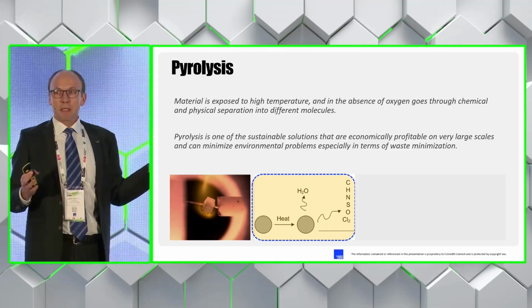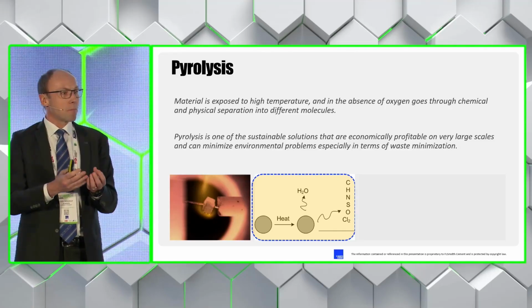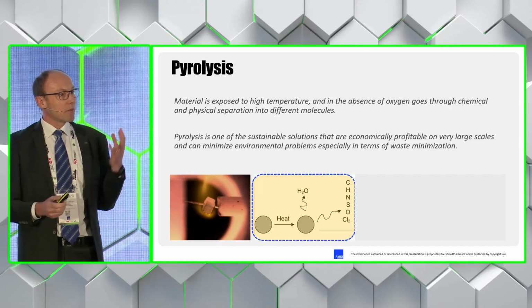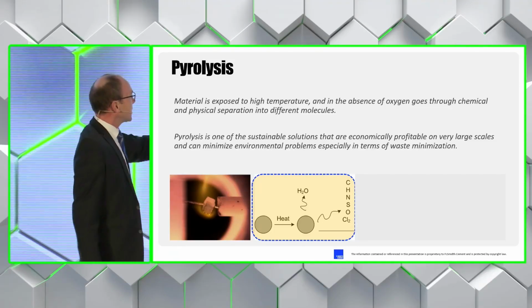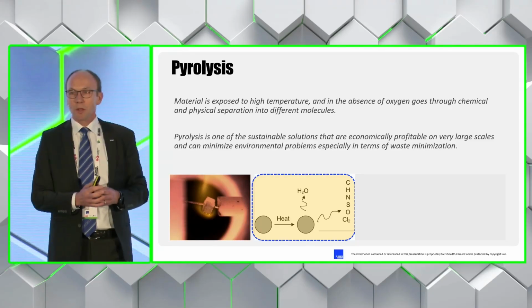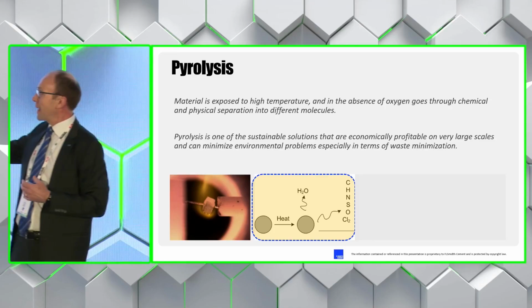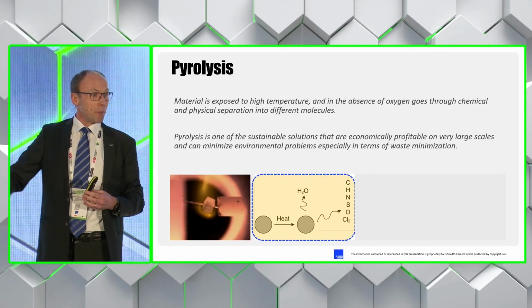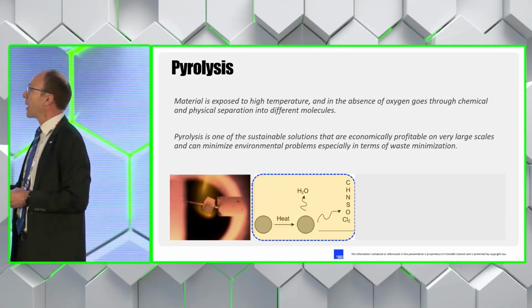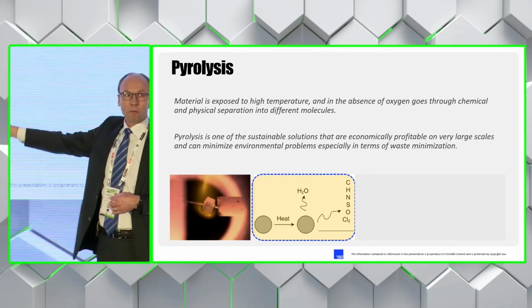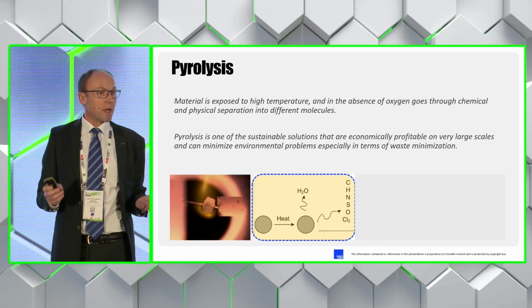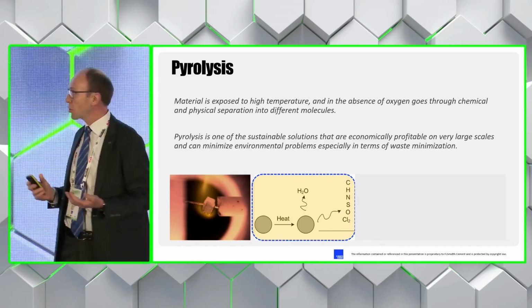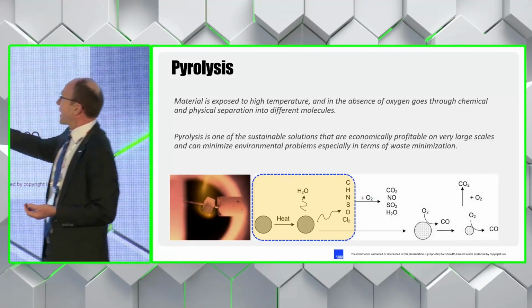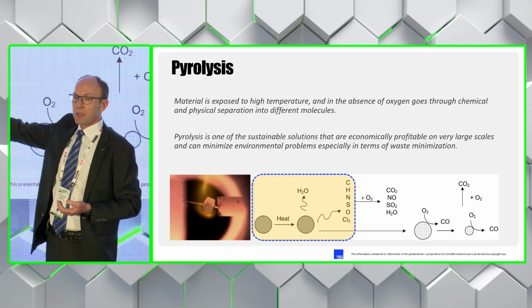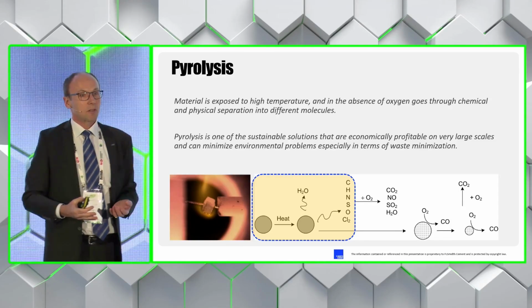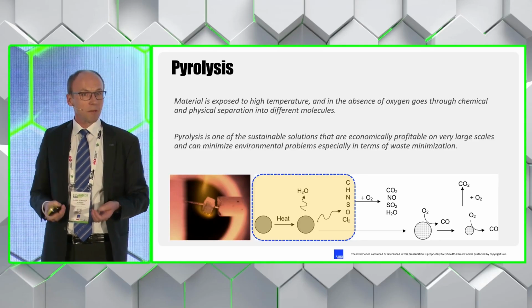If we look at pyrolysis, what that is, basically it's taking the fuel and then heating it up, breaking it down to form volatile components, and then the char. The bottom picture down here shows a piece of wood which is put into a laboratory furnace. When we then heat up this wood, initially the moisture evaporates from the wood, and then after that the volatile constituents are pushed off and it leaves the char behind. So this is basically what pyrolysis is, the first part of combustion, of most combustion processes. When we then add the oxygen, the volatile components and the char burn to form carbon dioxide and water, which releases the heat, which is what we need for the calcination.